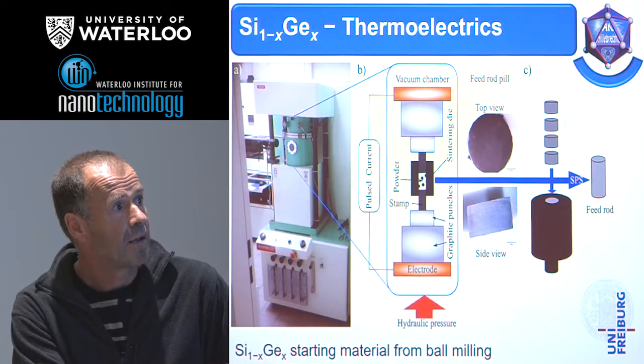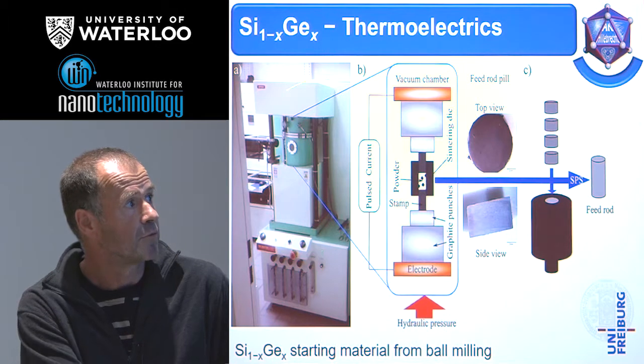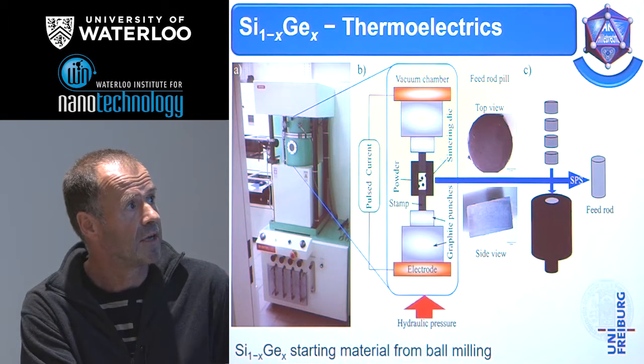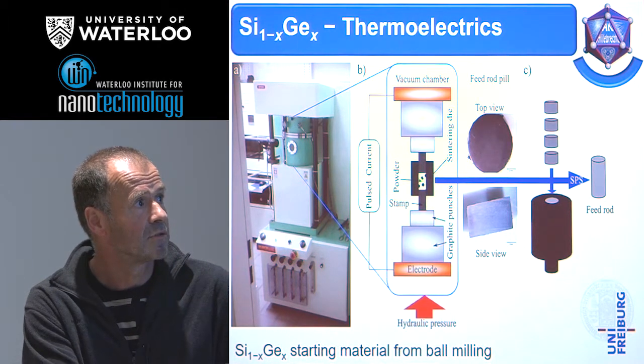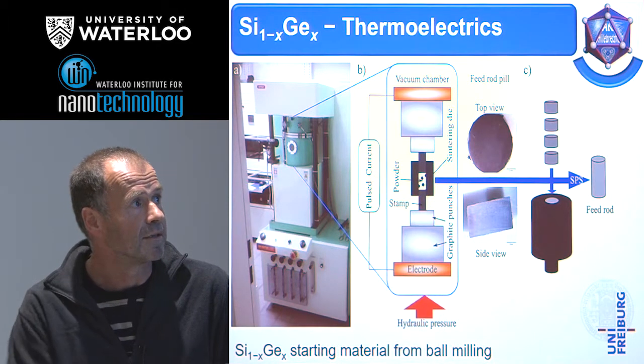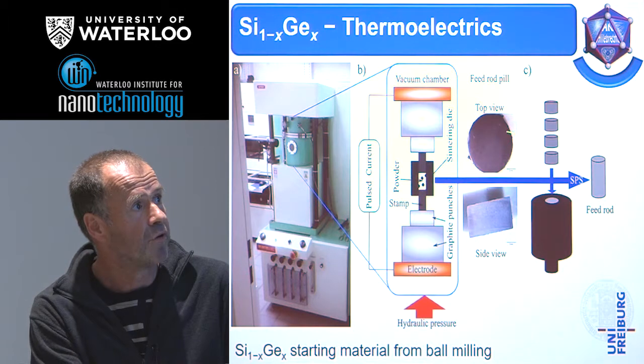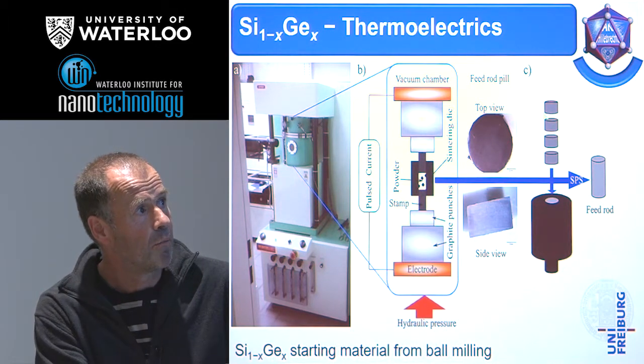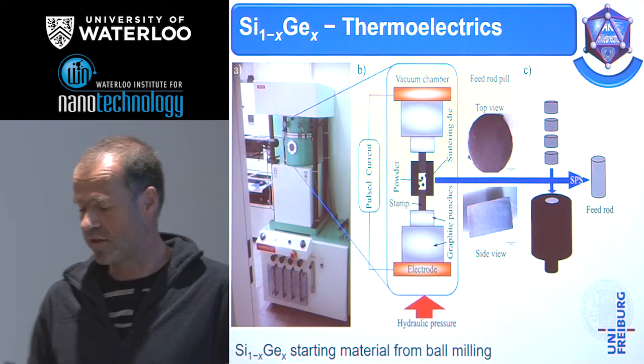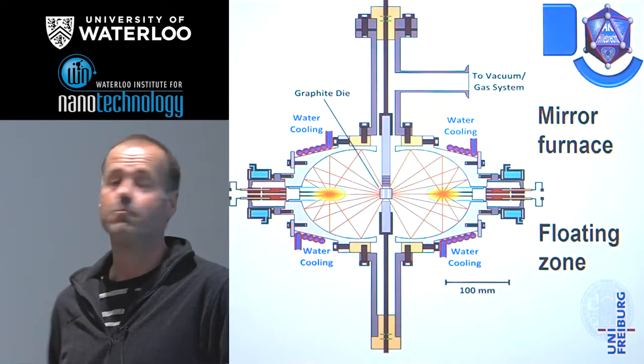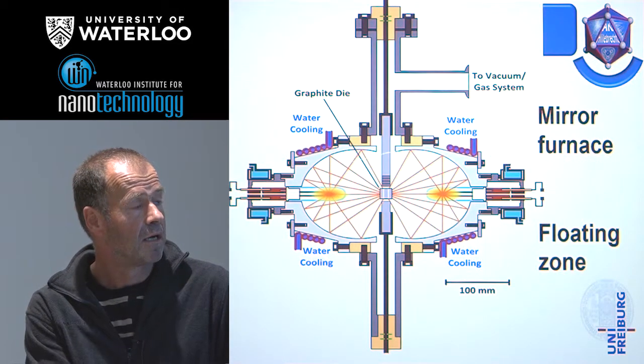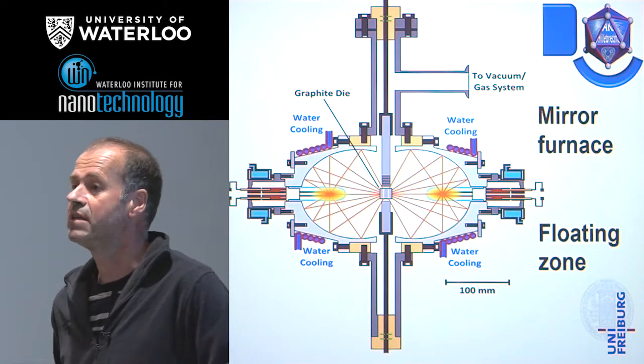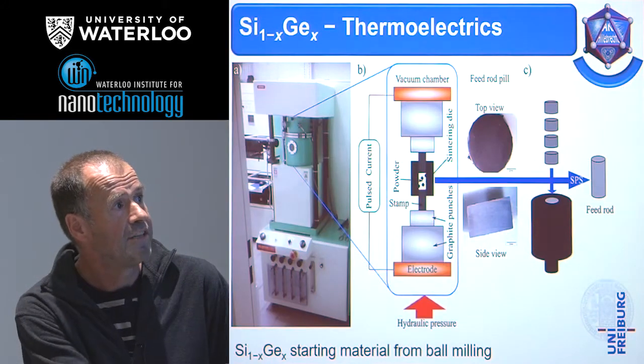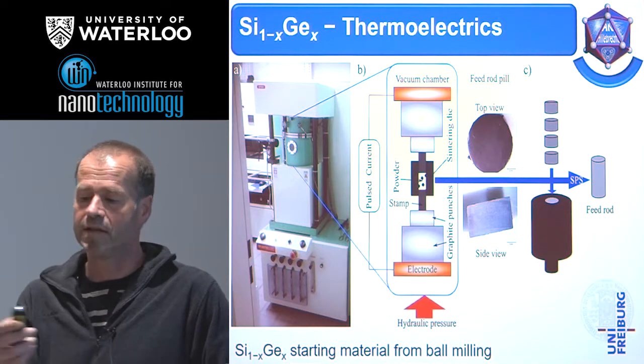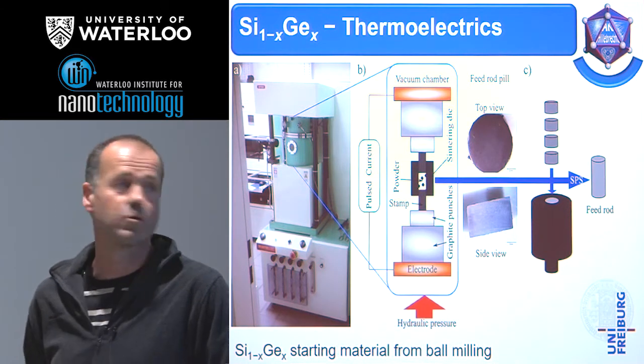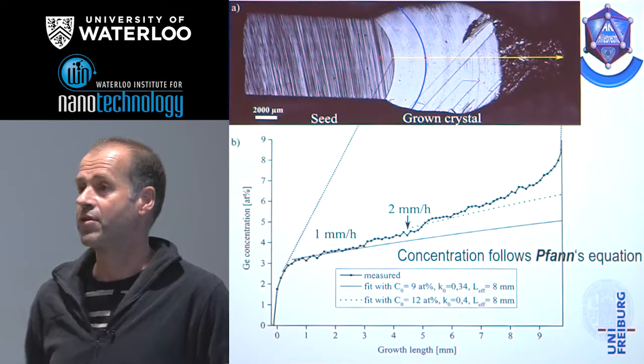We combine several pellets to a feed rod. This is our machine where we have the SPS device in it, and we have a graphite device to compress it, and a pressure chamber. And we see that we can produce well densified pellets, and we combine several pellets to a feed rod, and after that we start the single crystal growth in a mirror furnace with elliptical setup and do a floating zone single crystal growth, starting with these feed rods. And the general idea is to use well-defined pellets as a feed rod and to grow single crystals by the floating zone method. That works quite well.